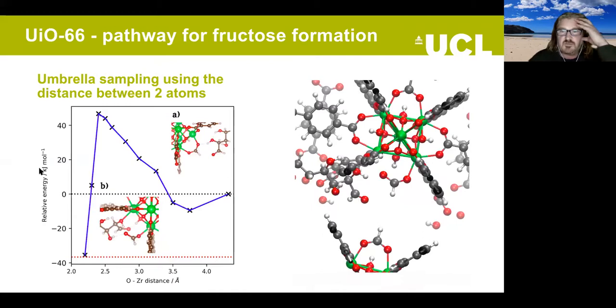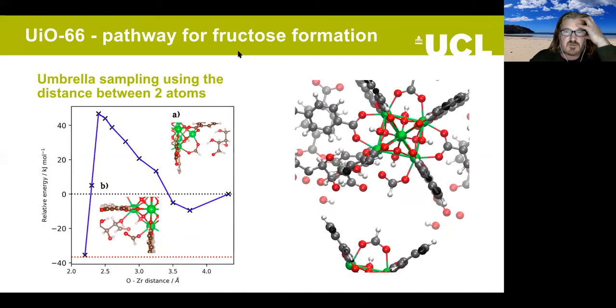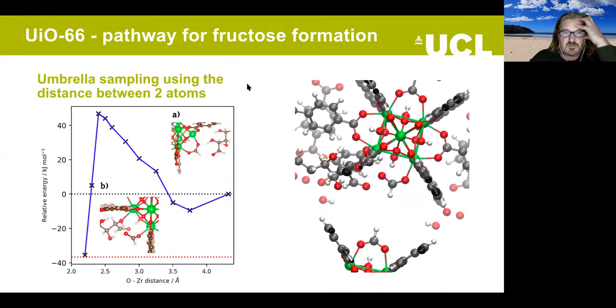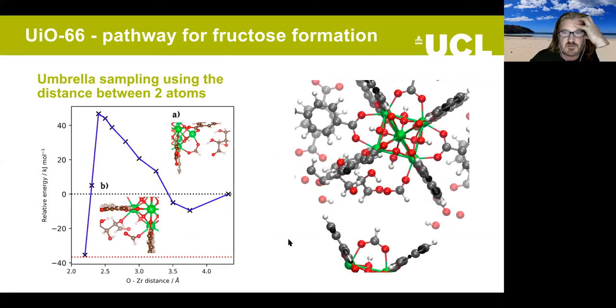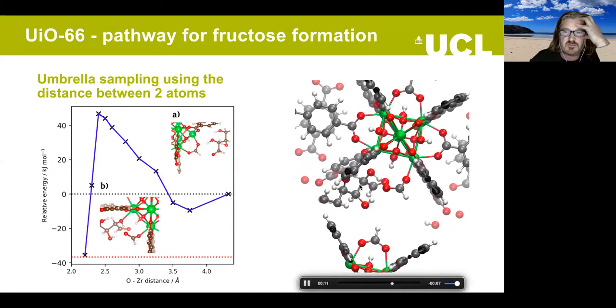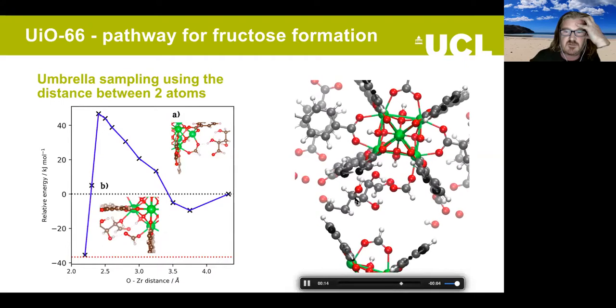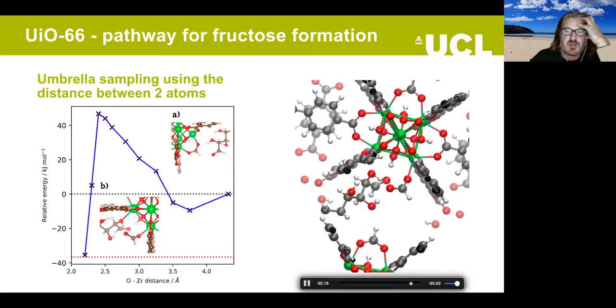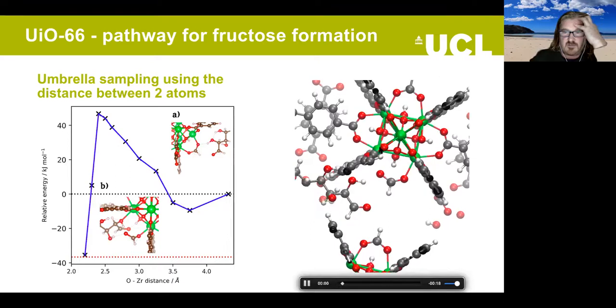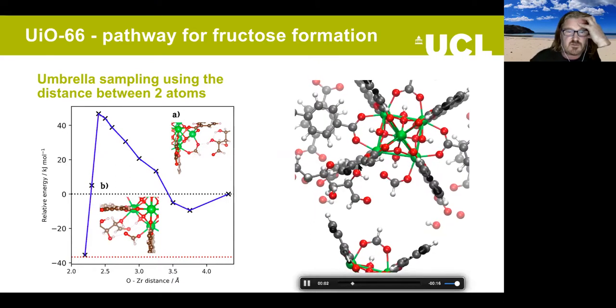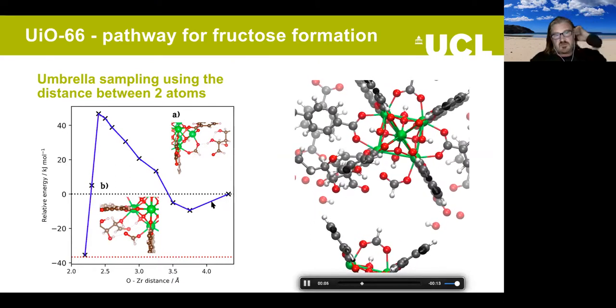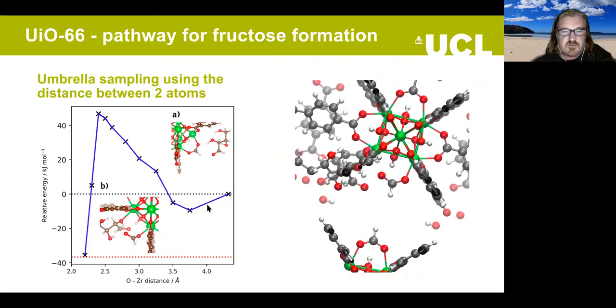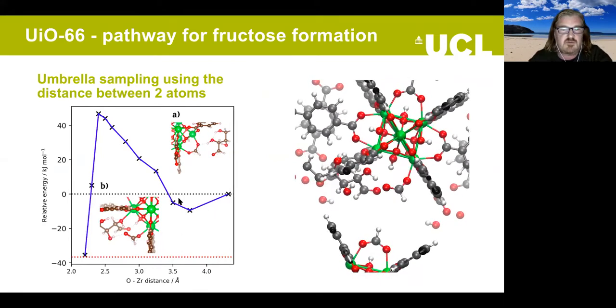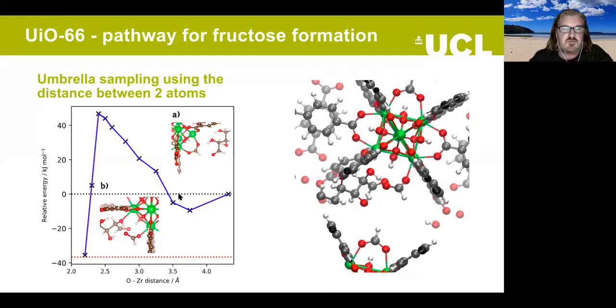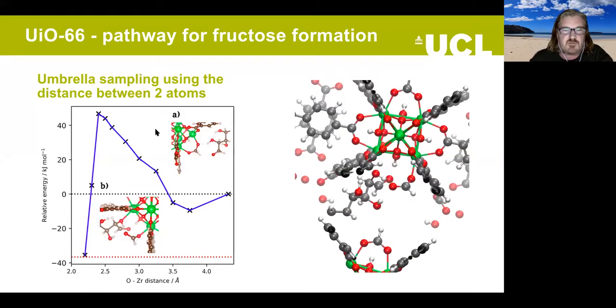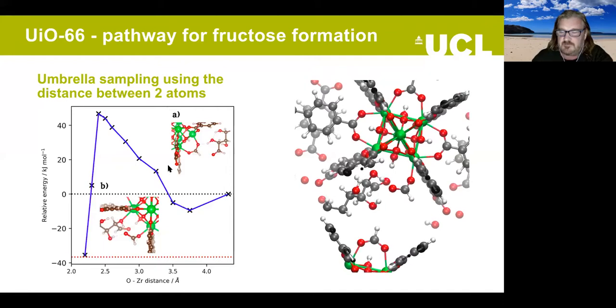We're doing work to understand actually the pathway for the fructose formation. This is work of Martin Hutero, and here we can see in this little movie, which comes from ab initio MD, some glucose which is attacking a defect site within the material, and we've mapped this out using umbrella sampling. And actually, it turns out that the initial step in this process for the formation of the fructose has a relatively small barrier associated with it.